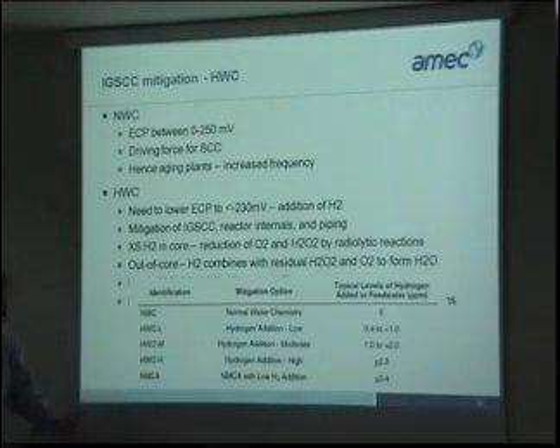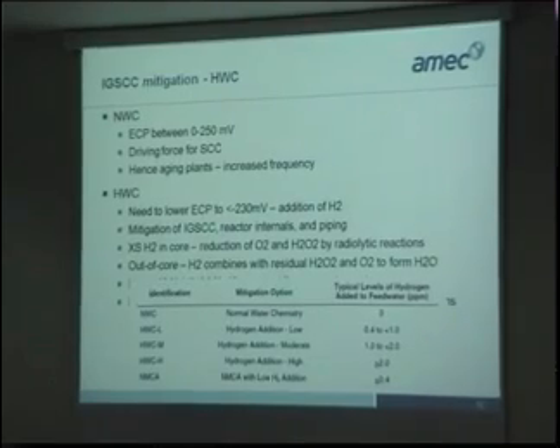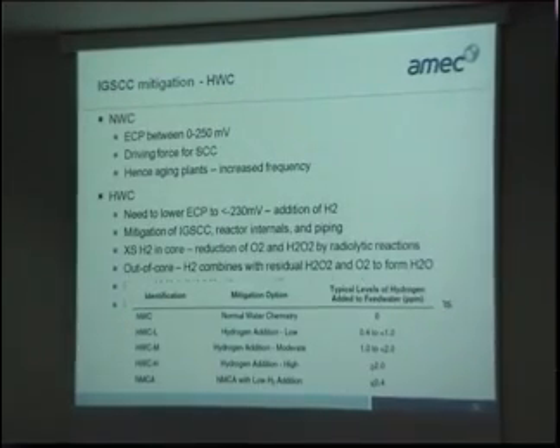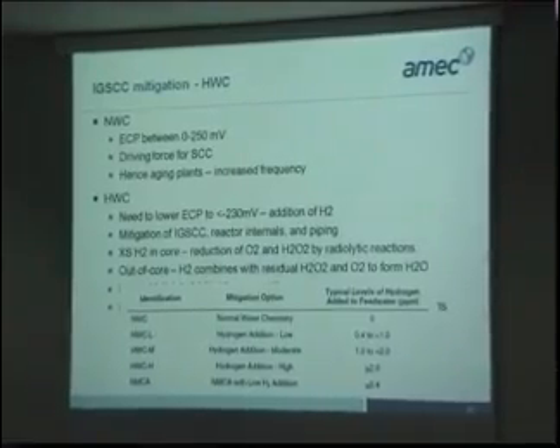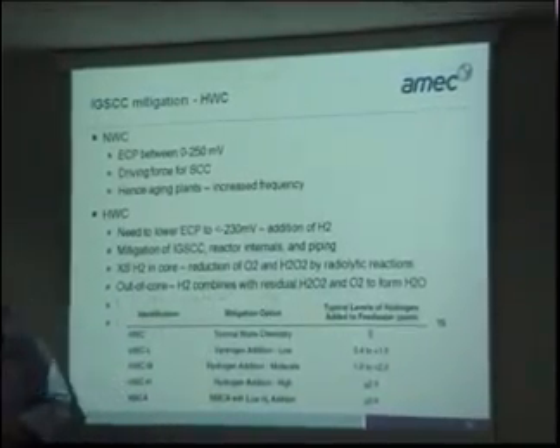We're going to talk a bit about noble metal chemical addition. This is, at the moment, dosed at shutdown to give a layer of a platinum or rhodium catalyst on a surface, and that's to encourage the hydrogen peroxide reaction. We add hydrogen to reduce the oxidizing species, but although it is a fairly rapid reaction, relatively speaking, in terms of the time scale of the core itself and the residence time, it is quite slow. So by adding a catalyst, rhodium or platinum, you can actually speed up that process, and in effect you can operate with less hydrogen.